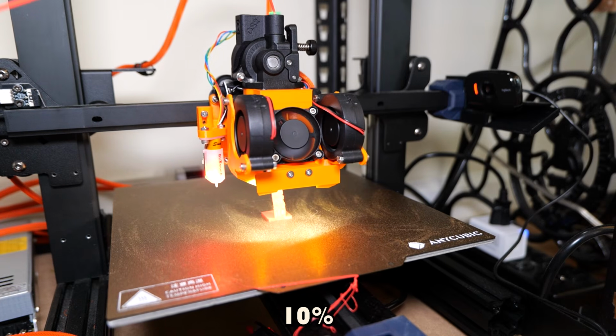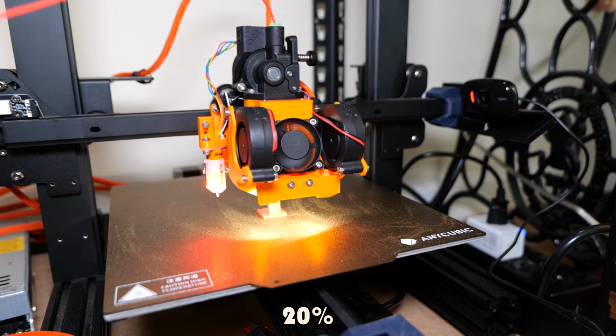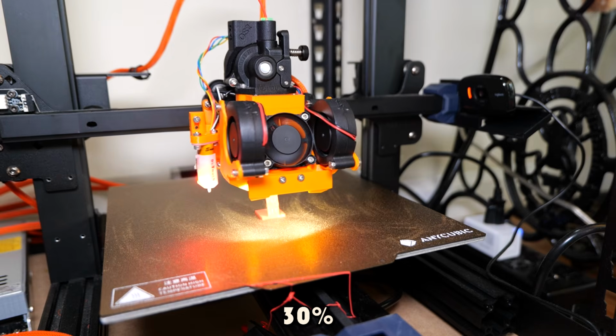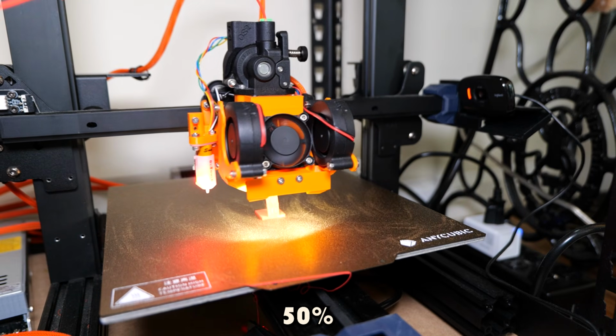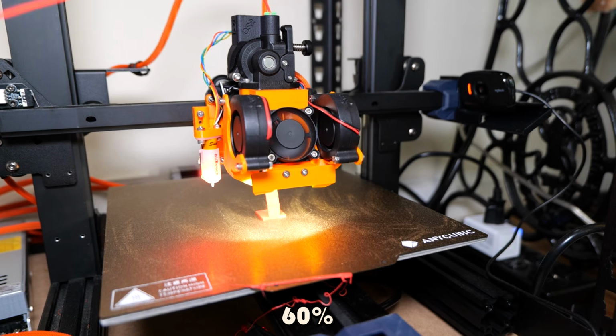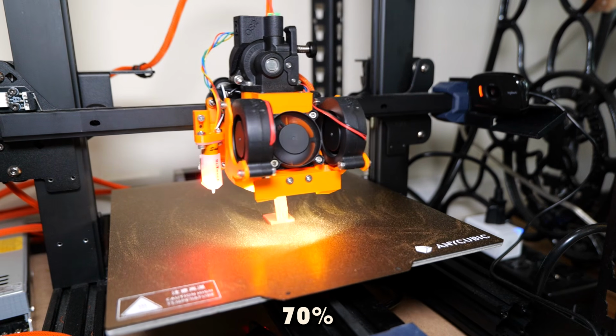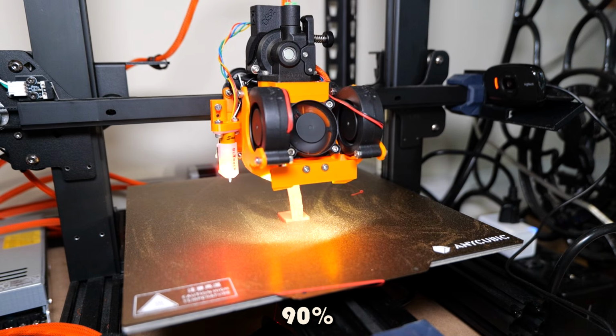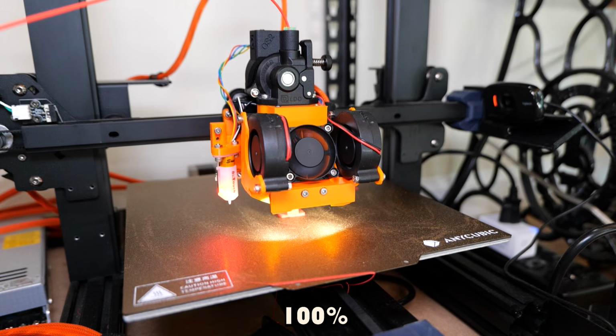For both the 200 Celsius and the 230 Celsius profile, I printed out these overhang tests from 10% fan speed up to 100% fan speed in increments of 10. So let's start out by listening to how loud the part cooling fans are at each fan speed. Now, let's check out the results of the overhang tests.